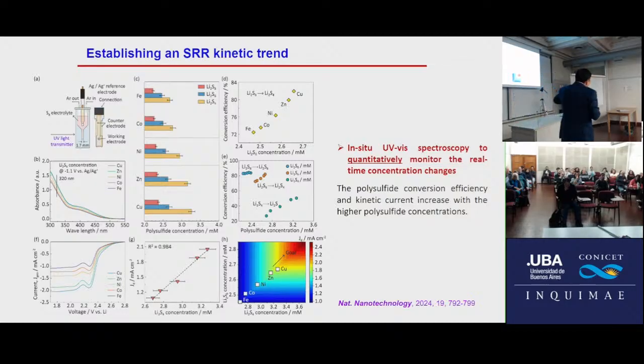Before this study, nobody could measure the concentration of polysulfide in the battery. My student established a new system using UV. He can measure the concentration, for example here at 1.1 voltage, at 320 nanometer, we can measure the signal. After that, we can measure the concentration of Li2S4. Similarly, we can measure the different polysulfide concentrations for different catalysts. After that, we can calculate conversion efficiency related to the polysulfide concentration, for the different reactions.